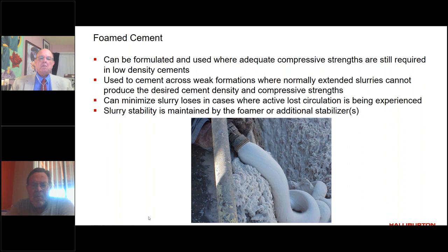We design the slurry for stability, for the specific density, and the foam is compressible in its nature, which means that it's very good at sealing off any lost circulation zones. And because we're not lightening it up by adding water, because we're adding a gas to it, it actually has better mechanical properties than a normal cement as well. Additional properties: it's very good with thermal insulation, so in high temperature wells, if you're worried about tubing stretch or pipe stretch, it's very good at thermal insulation, lost circulation, mechanical properties, meaning compressive strength, tensile strength as well. So foam cement is very applicable, not in every situation, but in certain more challenging situations where you want to cement. Next slide, please.